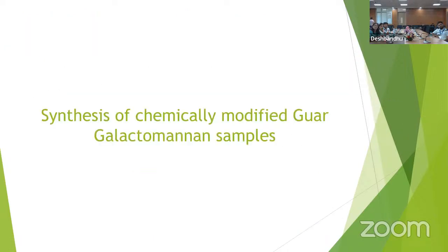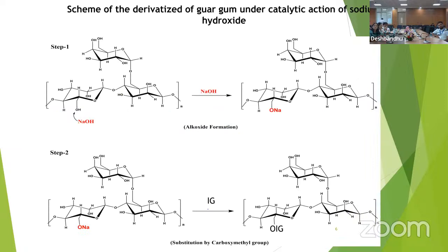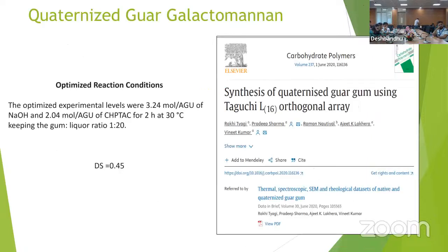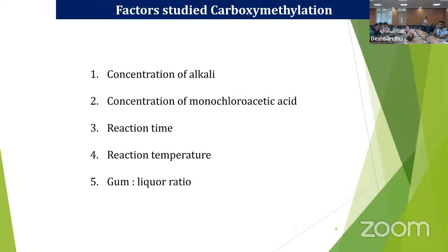This is a basic scheme for the chemical modification of guar gum under the catalytic activity of sodium hydroxide. The first step is the production of the alkoxide form of guar gum, followed by its reaction with an etherifying reagent. It was CHPTAC for quaternization, and in the present study of carboxymethylation, it was sodium monochloroacetate. For the quaternization reaction, I have already published a paper which details the optimization of reaction conditions and its spectroscopic characterization. As output of this study, we obtained a DS of 0.45, which is a measure of the efficiency of the reaction. These are the parameters which were also studied for the carboxymethylation process: concentration of alkali, reaction time, and so on.